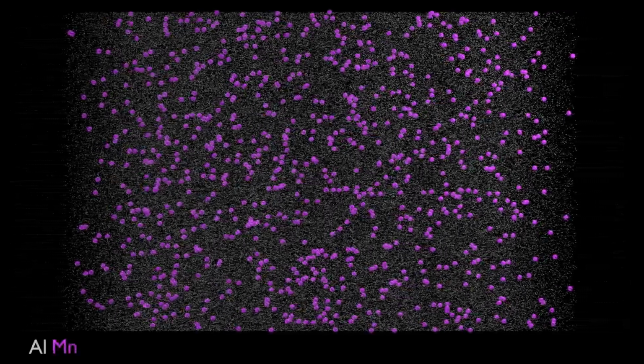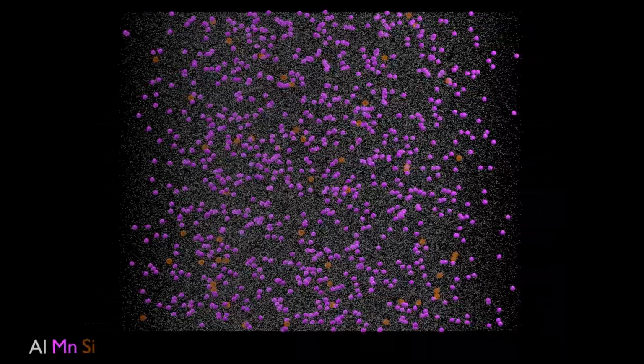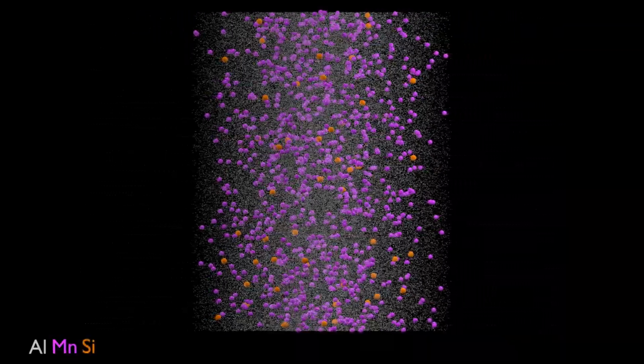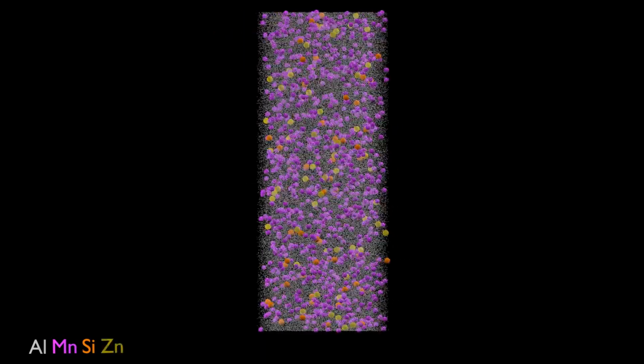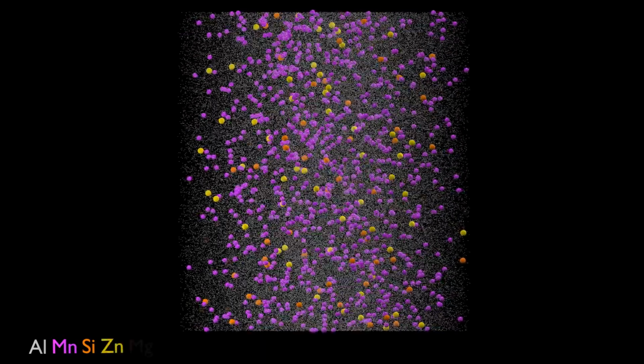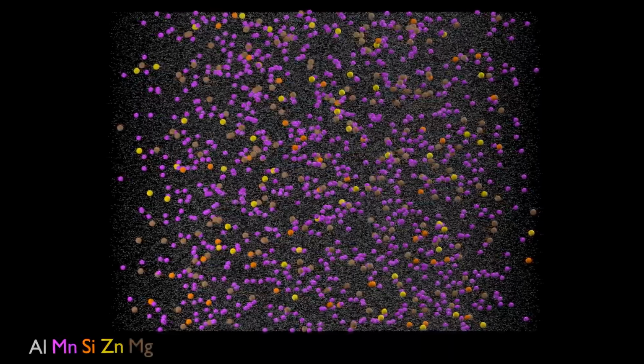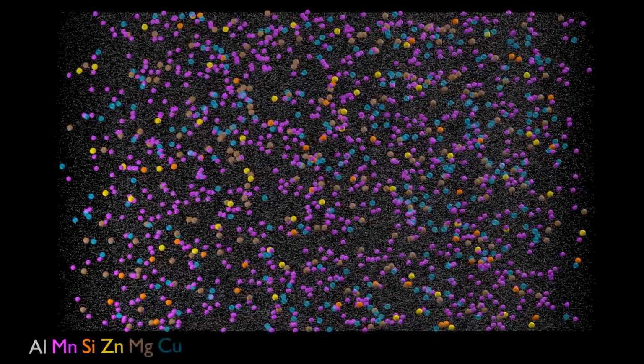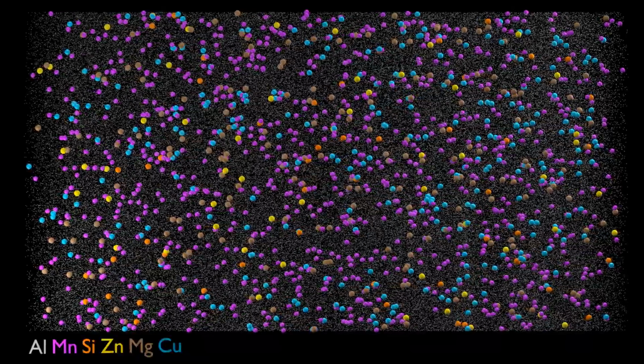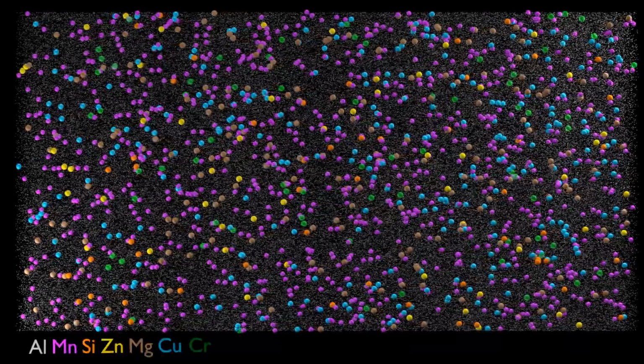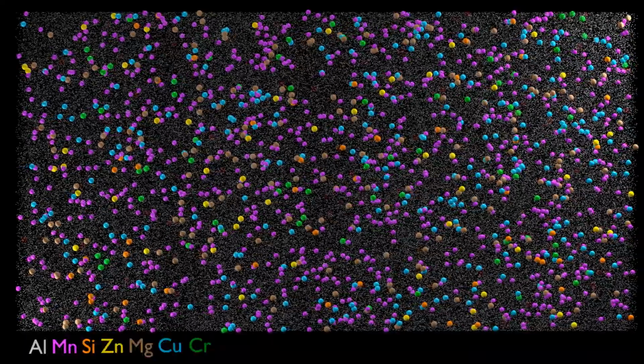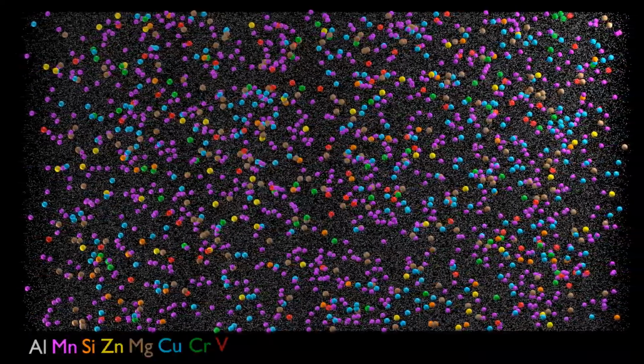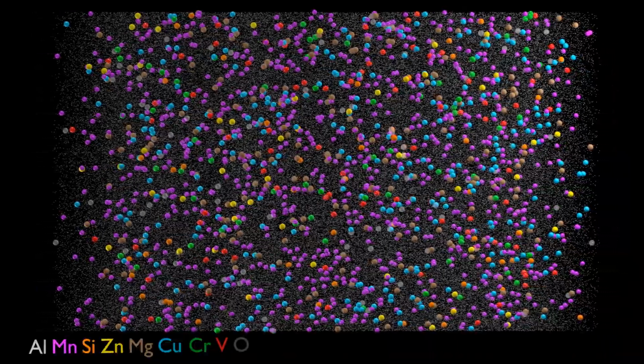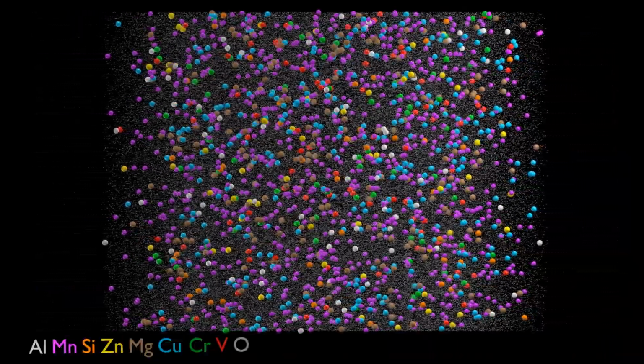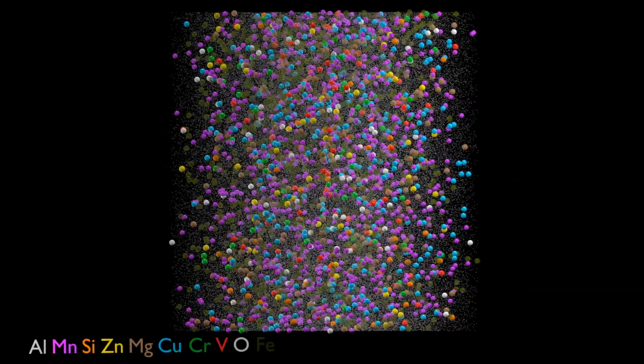This movie gives an example from a research project on impurity-tolerant aluminium alloys. It shows data from a tomographic atom probe measurement, conducted on a 3000 series manganese-containing aluminium alloy, used for drinking cans. Atom probe tomography is a method that allows to measure the chemical composition of complex materials at the near atomic scale. It works by combining ionization and field evaporation of atoms from tip-shaped sample surfaces under high electrical fields, combined with a mass-to-charge flight spectrometry and a position-sensitive multi-channel plate detector.